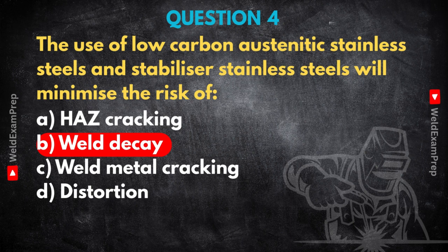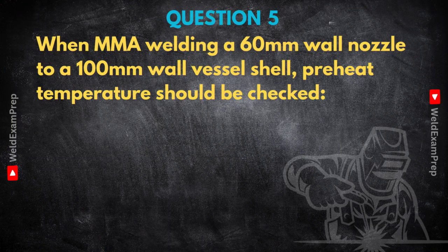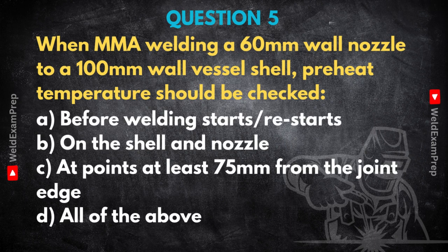Okay, one last scenario. Let's talk about a crucial preparation step, preheating, especially for thick sections. Imagine this. You're using MMA, stick welding, to join a pretty thick 60-millimeter wall nozzle to an even thicker 100-millimeter wall vessel shell. Heavy stuff, high stakes. To make sure the preheat is done correctly, when and where should that temperature be thoroughly checked? Should it be checked before welding starts and also before any restarts? Should it be checked on both the shell and the nozzle? Or should it be checked at points at least 75 millimeters away from the joint edge?